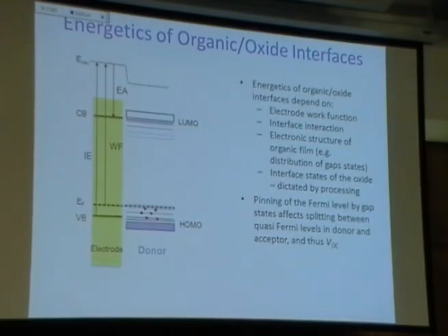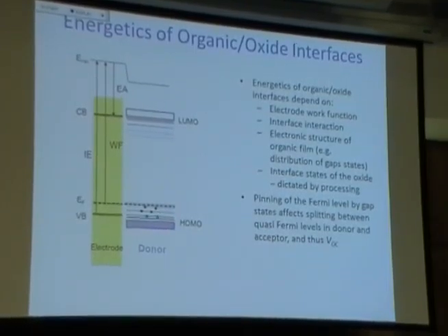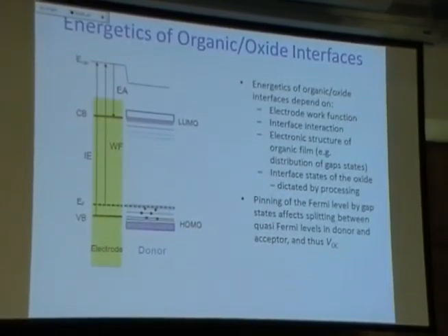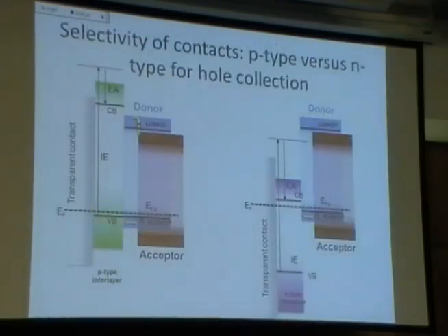From an electrochemistry perspective, the way I think about two materials is if they have different Fermi levels, when you bring them together, you have to achieve equilibrium. So you're going to have charge transfer that happens. Depending on how big the offsets are determines how much charge transfer you have. So we're going to look at what happens with work function, interface states, and again, this concept in the back of our minds that things are going to change.